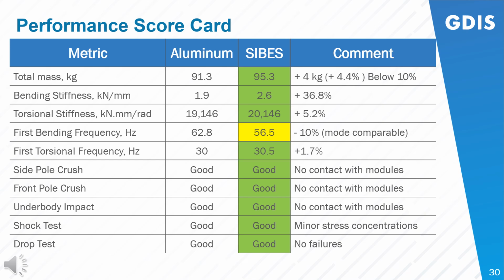First bending frequency is a little bit lagging, but again, as I indicated, it's not a refined concept. So again, with further refinement, this will probably improve. However, that said, really, when you think about it, with the rebalancing with the underbody, this may not be an issue. First torsional frequency is on par. And then, of course, all the other load cases, both the aluminum and the steel concepts are good.